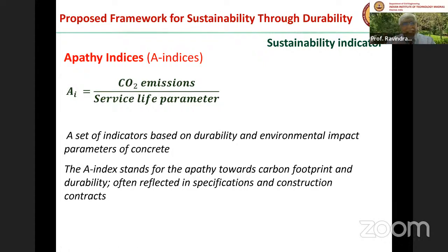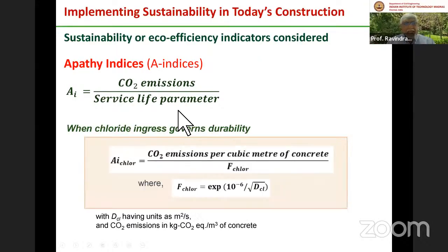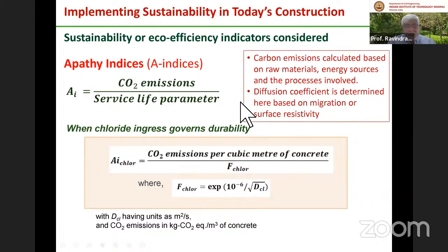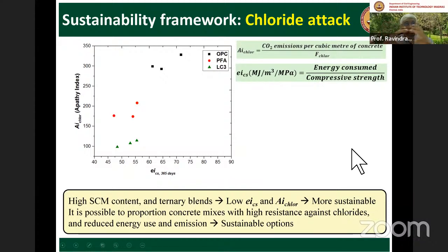Very importantly, we have defined a second set of indicators called apathy indices, which divides the carbon footprint by a service life parameter. And this could vary depending on the attack you have. So say if you have chloride attack, chloride ingress is governing the durability. Then the apathy index is the carbon footprint divided by a factor that depends on the chloride diffusion. You see the chloride diffusion coefficient here. So with this, we have brought in on one side the energy and the mechanical integrity, and on the other side, we are bringing in carbon emissions and the durability. So with this, we believe that we can see if a material, a concrete, is more sustainable or not.